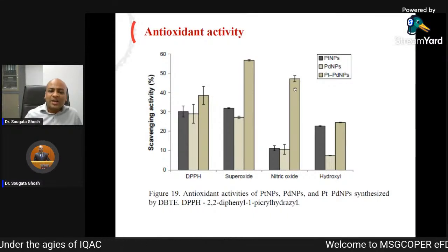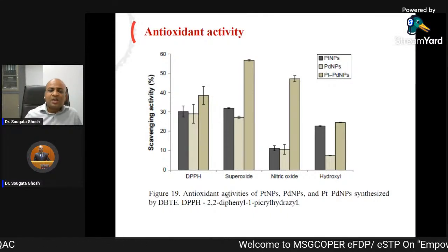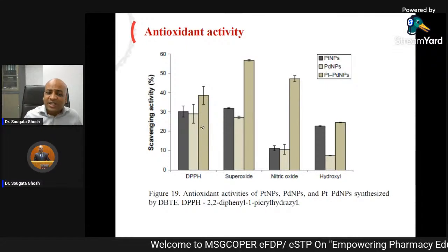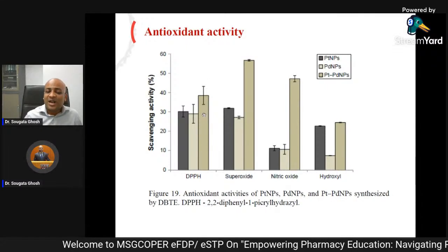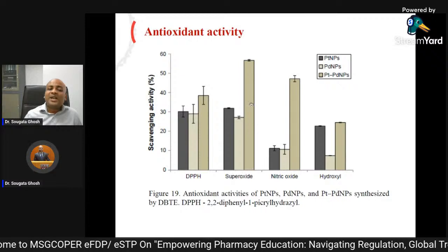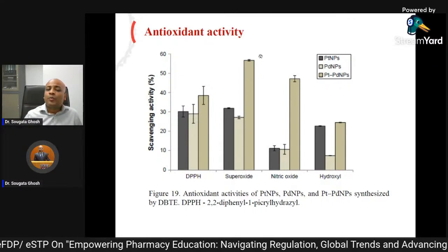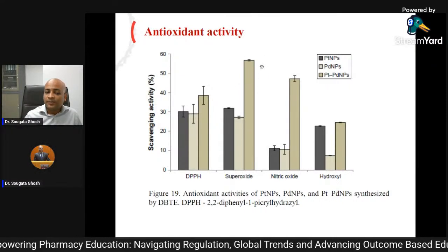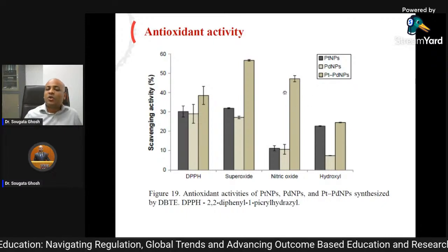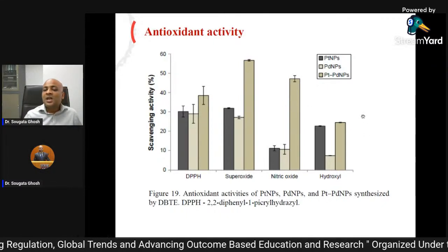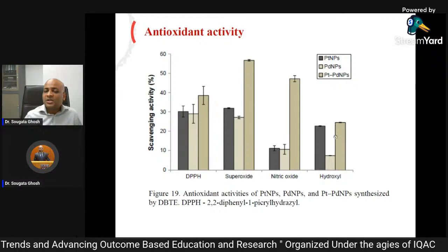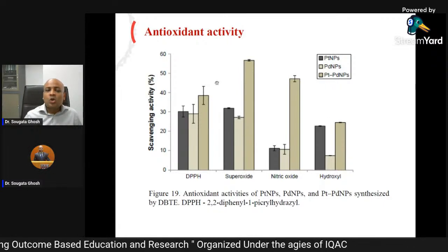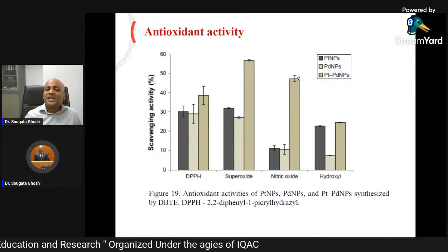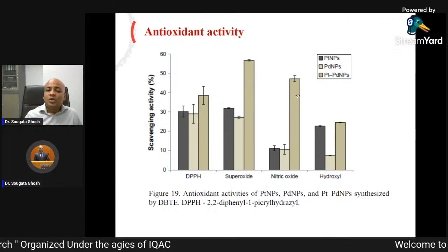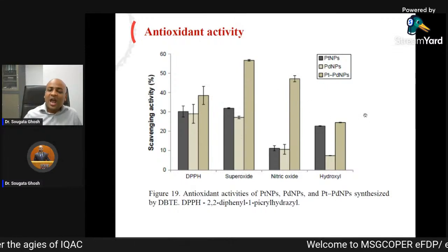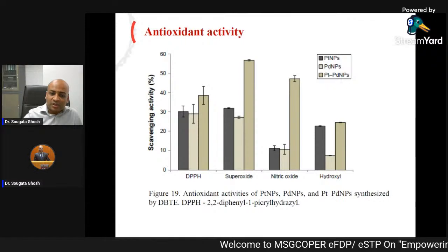So when we are adding platinum, palladium and together, we could see bimetallic nanoparticle were scavenging this DPPH radical more. Bimetallic nanoparticle was showing highest superoxide radical scavenging activity, highest nitric oxide radical scavenging activity, and very high hydroxyl radical scavenging activity. So this meant this bimetallic nanoparticle is a very good free radical scavenger and can protect from oxidative stress.